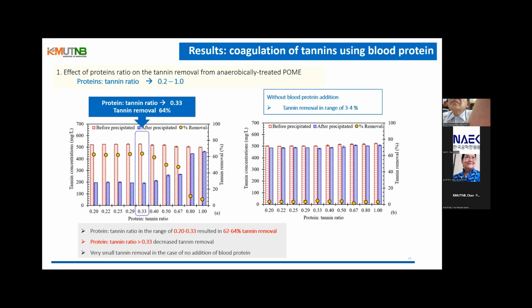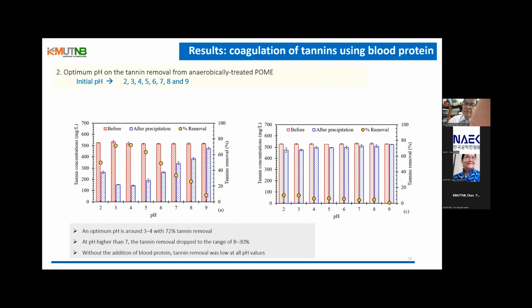The figure shows tannin removal as a function of initial pH between 2 and 9. The increase in pH from 2 to 4 caused the tannin removal to increase from 50 to 72%, whereas a further increase in the pH reduced the tannin removal.